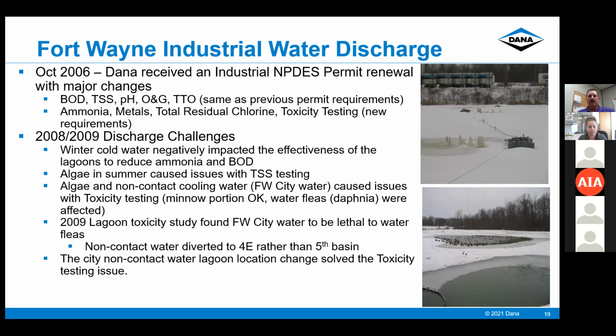And that test started causing us some issues. We couldn't understand. We had fish in our lagoon system. We had daphnia in our lagoon system, but we were having trouble passing this test to show that there was no effect to the daphnia. In 2009, we performed a toxicity study to determine why we were having trouble with this test, and found out the Fort Wayne city water we used as non-contact cooling water that was placed into our lagoon system was lethal within 24 hours to the water fleas. So now we understood that our non-contact cooling water, the city drinking water that we were putting into our lagoons, would kill our daphnia and prevent it from passing the test.